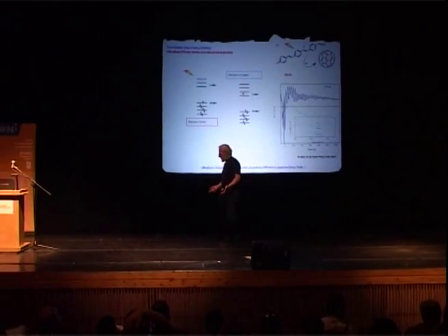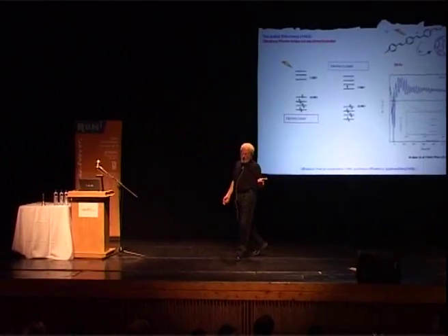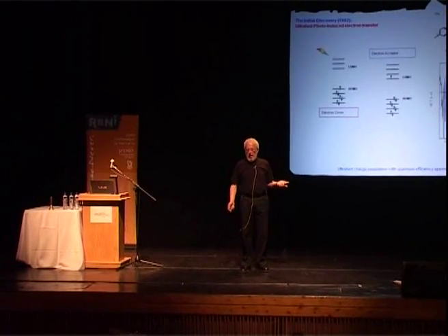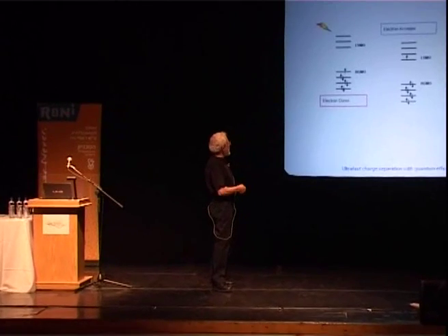Now, how fast is it? What difference does it make? Well, the answer is that there's no competing reaction. Many of these polymers have some luminescence, and a typical photoluminescence decay time will be several hundred picoseconds, even close to a nanosecond, but say 100 picoseconds. In other words, 3 orders of magnitude slower than this charge transfer time. So the quantum efficiency for the charge transfer approaches 100%.